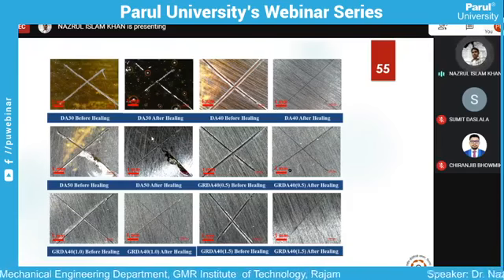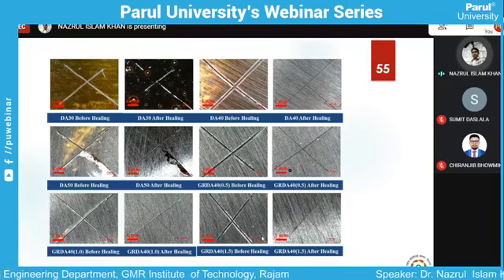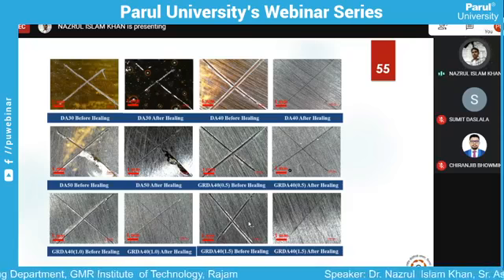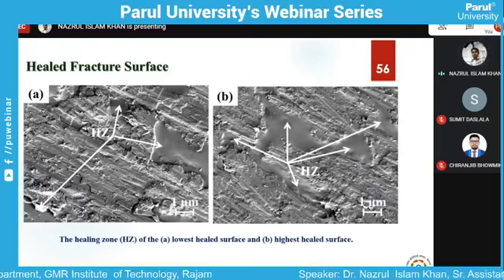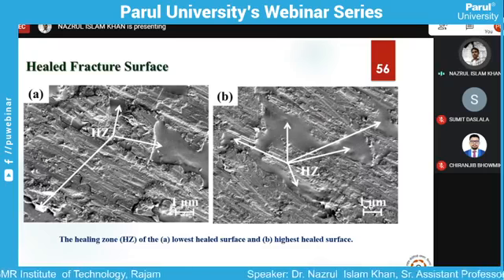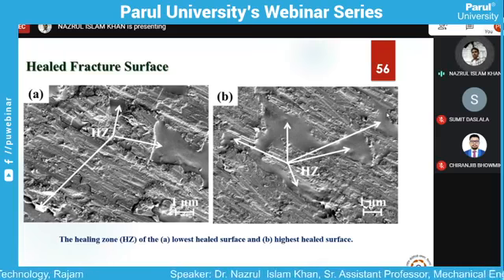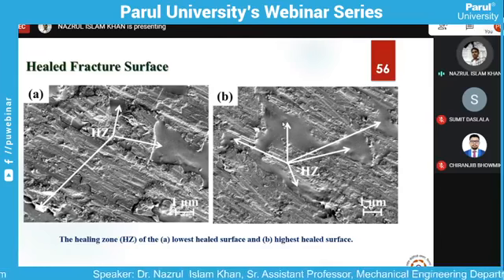From the scratch test also we were able to get the healing visually, but we were not able to quantify it; we could only visually compare the results. On the high resolution microscope, FESEM, we have seen that due to breaking of the microcapsule, some resin and hardener has flown on the surface. These are some resin and hardener wetted zones you can see, and these are the regions behind our self-healing taking place.